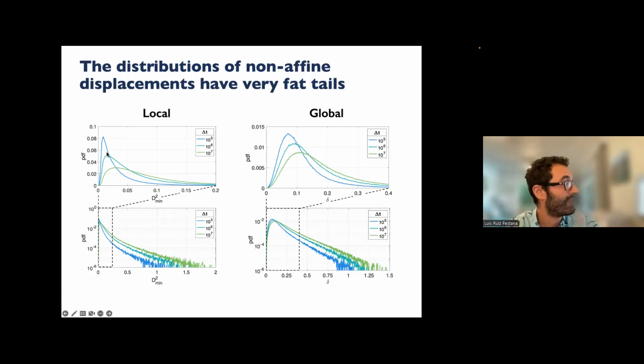If you look at the top left plot, over time, going from blue to green, the distribution becomes broader and the average displacement shifts to the right. Also, the tails become thicker. This makes sense, right? As you deform the material, the displacement of the particles with respect to the initial configuration increases. Now, the local and global displacements show the same trends. They look slightly different because they are different measurements, but they show the same trend.